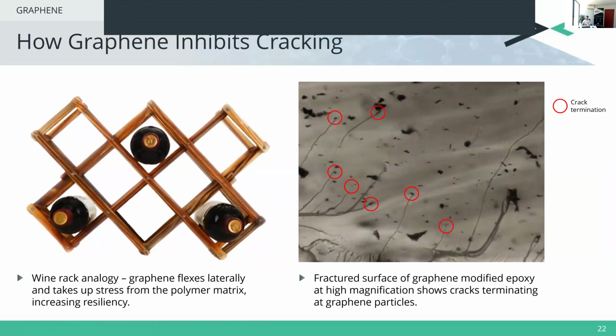And why I say that is because of how graphene is working, and we were the first company to really show this definitively, I feel, within the coatings industry. And it's working as a shock absorber effectively within the coating. Graphene is 200 times stronger than steel, along with being flexible and having a number of other wonderful properties. But within a coating, what we see is when a coating is put under stress, we see micro cracks. Those cracks propagate until the graphene particles, which are the black particles that you see on the right-hand side, and then they stop. So they're effectively acting as a shock absorber within the coating, and that is meaning less cracking. You only get corrosion where you have defects and cracking within a coating. So that is the key mechanism, we believe, why graphene and our graphene-based additive is improving the durability of these heavy-duty anti-corrosive coatings.